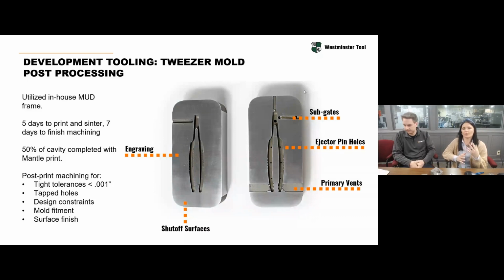So when I say I had 50% of the cavity complete, it's not the part geometry that I had to do. These were just the additional operations that you need in order to make an injection mold work. In general, with Mantle, the post-processing that we have to do is for tight tolerances. So if that 1 thou isn't sufficient, then you'd have to go in and achieve that. Also tapping holes, any design constraints that we might not be able to achieve, mold fitment and surface finish. Like we've mentioned multiple times, it comes off at a D2 EDM finish. So if you do need a B or an A finish, then you'd have to polish that.